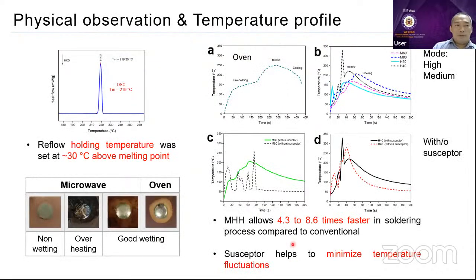For your information, we ran the DSC. We found that normally the reflow temperature is about 220, something like that. So this is the reflow. Even though we are using a microwave oven, we hope that we can reach these temperatures.